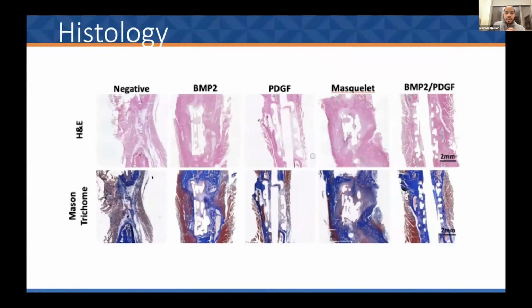So here's our histo. Basically, we had different groups that I mentioned prior. And I like to look at this row on the bottom here, and blue is bone, basically. And essentially, when we had BMP and platelet-derived growth factor, we were able to see bridging bone between the bone ends, which you don't really see as well in the negative control. You do see it with the BMP only. PDGF only, not so much, and the Masquelet just looks kind of disorganized, but may or may not have some bridging bone.